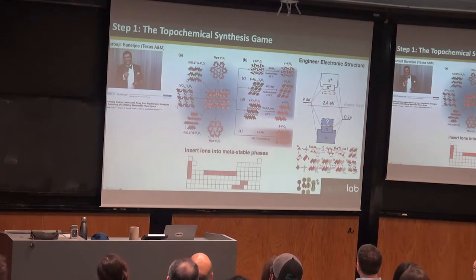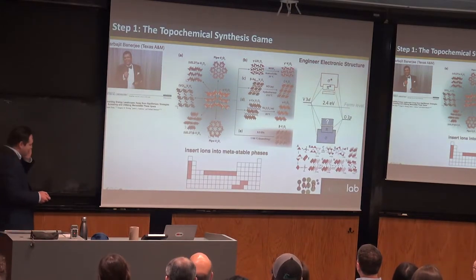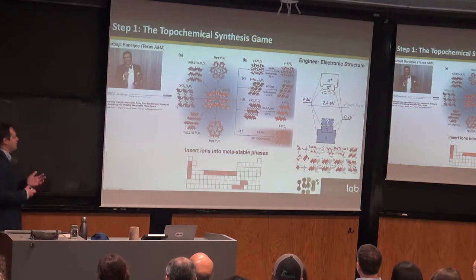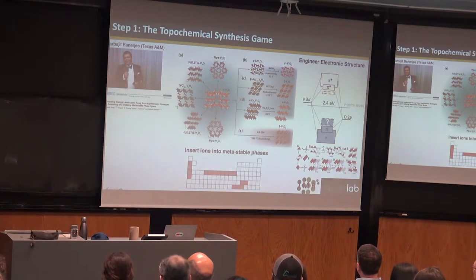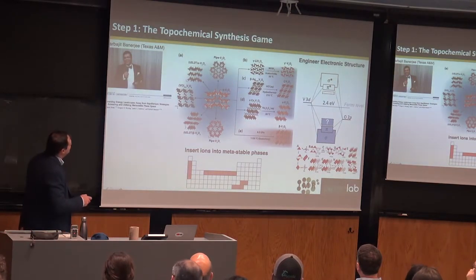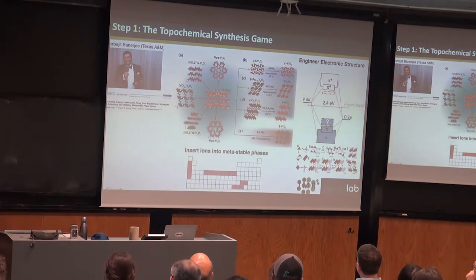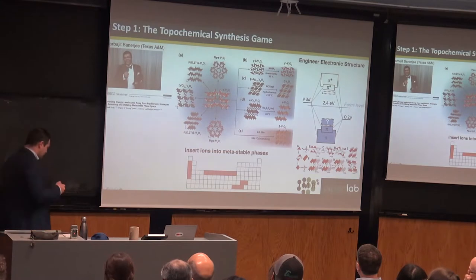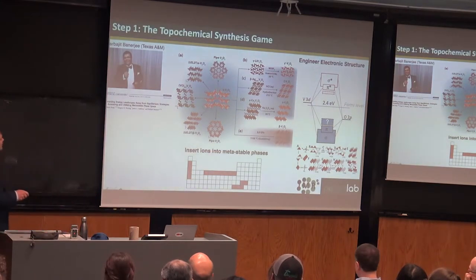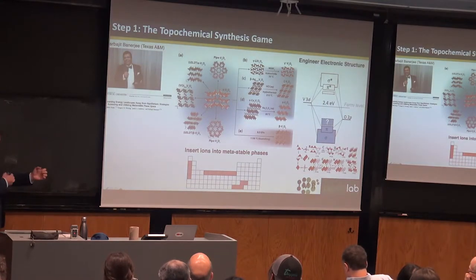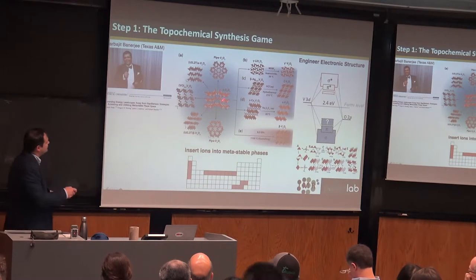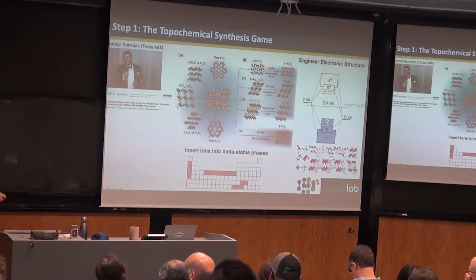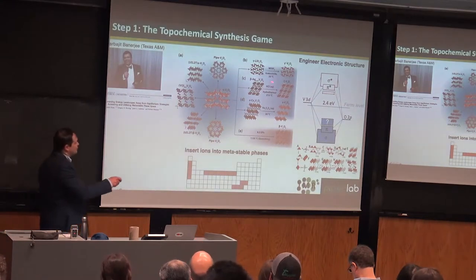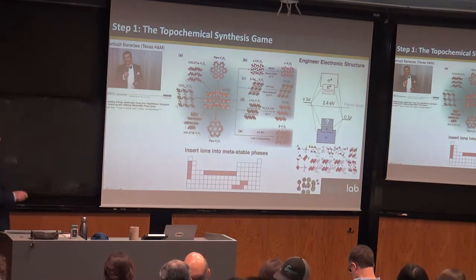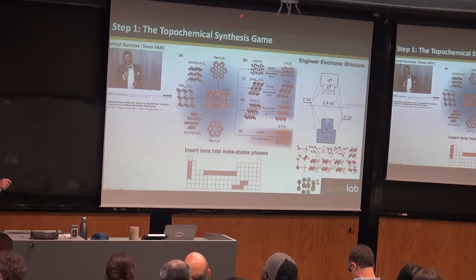So the alternative is a topochemical game, where we do topochemical synthesis. So the idea with the strain game is you get a large playground for physics. In this case, it's a large playground for chemistry as well, in the sense that my collaborator, Subhajit Banerjee at Texas A&M, had spent a lot of time working on vanadium oxide systems where you can essentially take a system, leach out the ions, form metastable host compounds of different polymorphs, and then reinsert your desired ion into that polymorph. So it opens up a whole range of polymorphs, a whole range of ions, because you can put in things as light as lithium all the way down to lead.